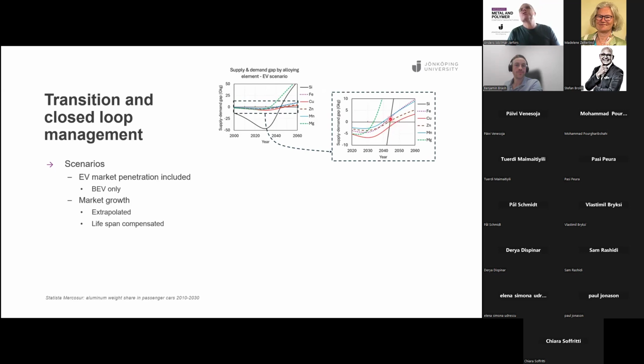And there's a dramatic change here. So somewhere about 2045 or something like that, you pass where you also have a surplus of silicon, which would then affect the carbon footprint. Because if you can match your alloys, which is one of the challenges that Benjamin mentioned, you would actually have enough alloying elements in the scrap coming back. So you would only have to work with that mix and then be able to just add the aluminium in nice proportions. But that requires that we have enough understanding of what actually comes, how it's being sorted, and what we can achieve with that mix that we have coming in.